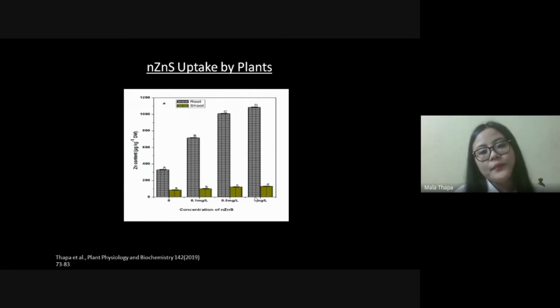Now, to study the uptake of nanoparticle by plant, we have measured zinc content inside the plant tissue and found that significant increase in zinc content found in root and shoot of treated plant in comparison with the control, which again confirm the uptake of nanoparticle by the plants.